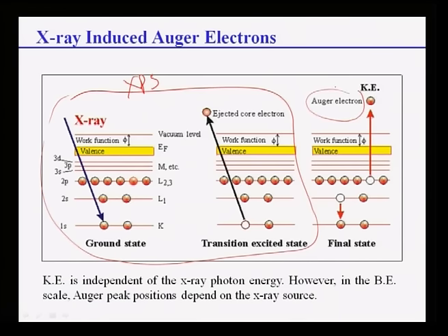That means the values of this spin orbital splitting, this is the spin orbital splitting value, for a core level electron in different compounds are nearly the same. Peak area ratios, that means this is the peak area for these two electrons. Peak area ratios of a core level of an element in different compounds are also nearly the same. These two are very important.